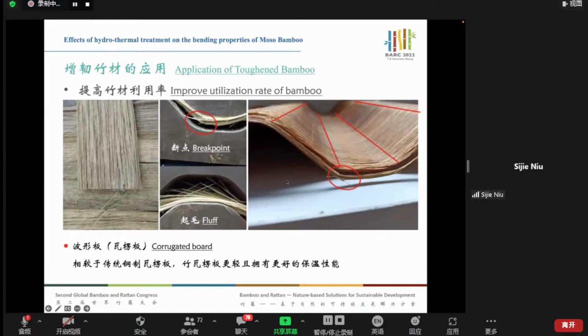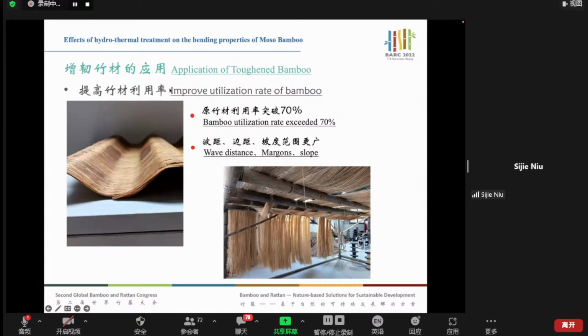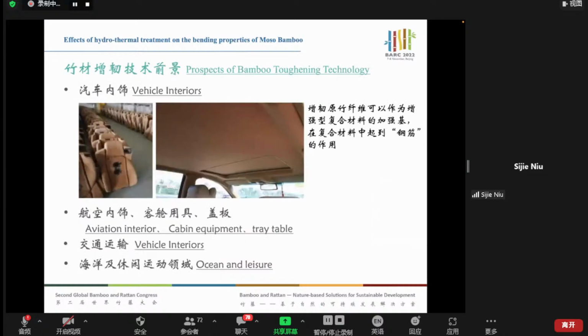You can see once the radius of curvature is the largest, then the toughness of the bamboo is the minimum. But our solution is toughened treatment. After this treatment, we can improve the utilization rate by 70%. Of course, this is only a lab test result. Secondly, we can have a wider selection on the wave distance, margins, and slopes.